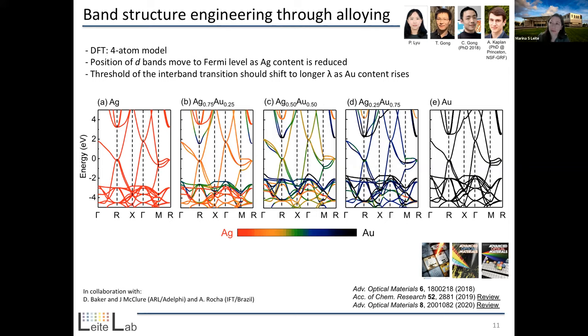And there's a lot of work that went into that, and I'm not going into a whole lot of details here. But let me just summarize by saying that we basically could then quantify that the threshold here for an interband transition should shift to longer wavelength as we increase the amount of gold. We go from red to black. And this is something that we could test in the lab by doing transmission measurements, literally shining light through our thin film and glass, and seeing how much light is actually transmitted, and correlate these two, I would say, in a semi-quantitative way. Okay. And this was very rewarding for us because then we could correlate what you're seeing through the optical measurements in the lab and the permittivity measurements, especially epsilon 2, and all the transitions that can happen within these alloys.